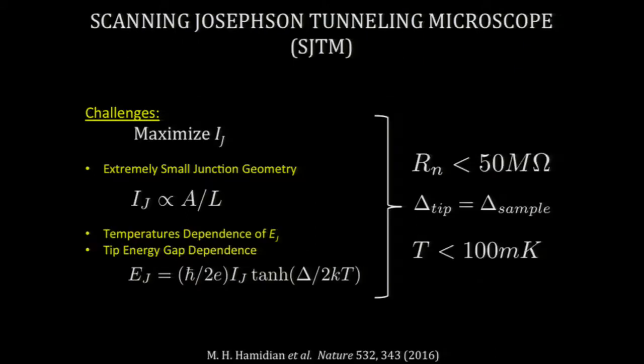So what we really want to do is to measure that quantity with a scanning probe so that we can see the spatial structure of the superconducting order parameter. And this ends up being a rather challenging thing to do because we want to maximize I sub J. If you maximize the critical current, then you can have a better signal to grab. But if you're trying to do it with a scanning probe where you're trying to get that probe size to be on the nanometer scale, I sub J scales as the cross-sectional area of the Josephson junction divided by the distance between the two superconductors. So the smaller you make your probe, the smaller that's going to become.